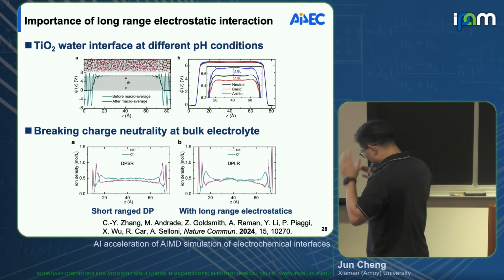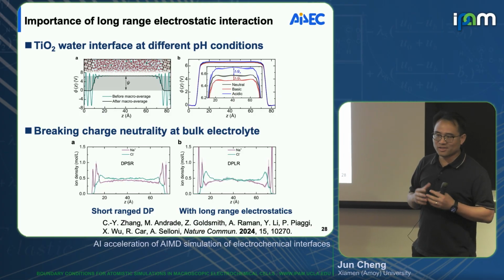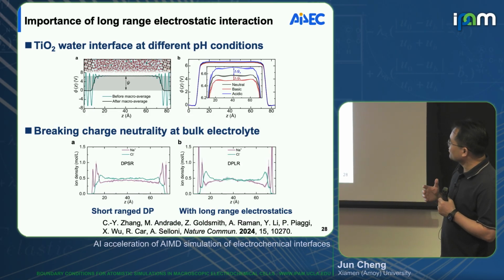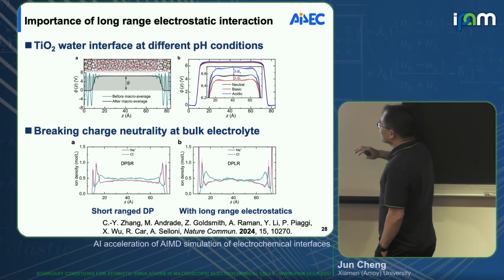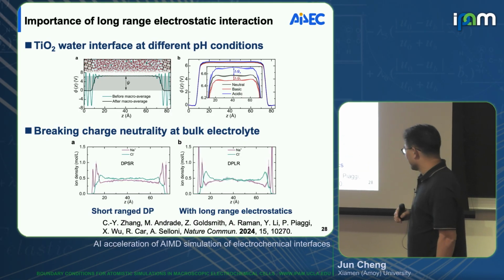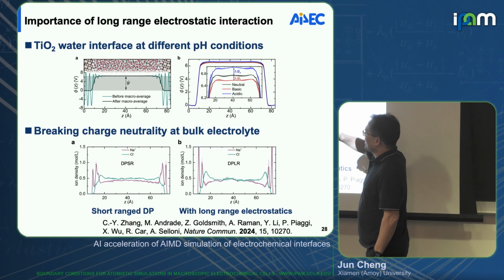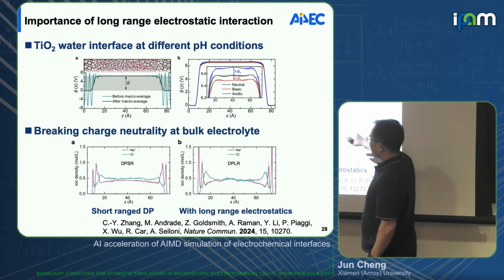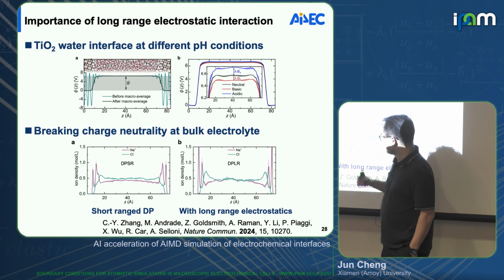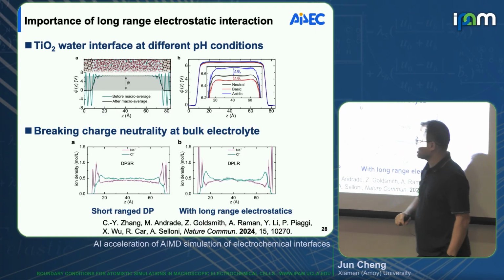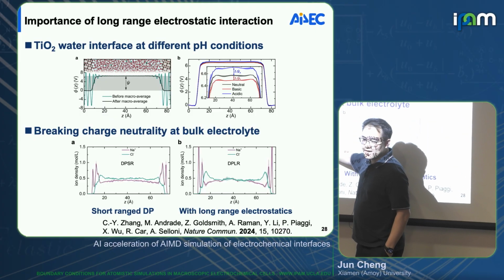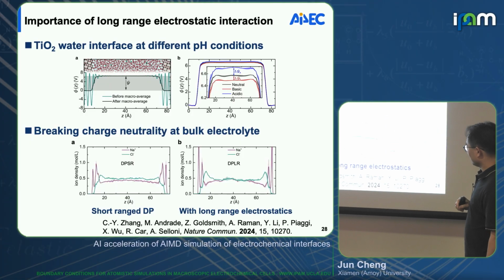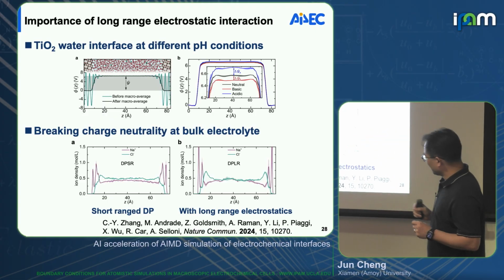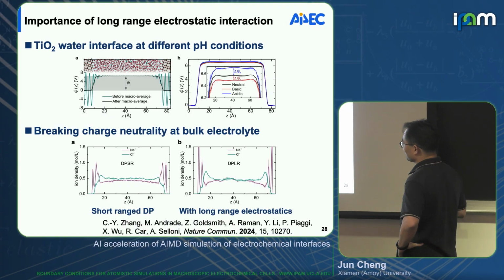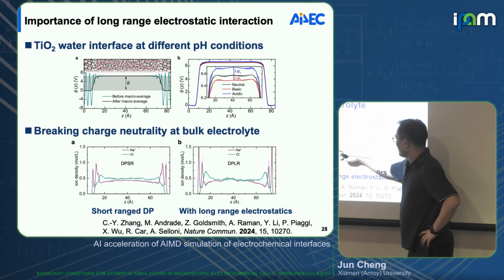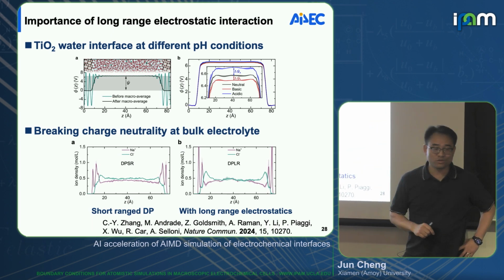We all know the machine learning potential is good, but all the previous work is based on this local representation, right? That's also due to the efficiency. I'm sure many people are using this. But for electrochemical systems, it's certainly not enough. That's the work that was shown by Andrade, a charged TiO2 water interface. They show that if you use the short range machine learning potential, the deep potential, you even break the charge neutrality in the bulk electrolyte. That's the distribution of the cation and anion. You have a mismatch in the bulk solution. So that's certainly not enough. The electrostatics is not well respected by the short range machine learning potential. And with the long range DPLR, they can recover this charge neutrality in the bulk solution.